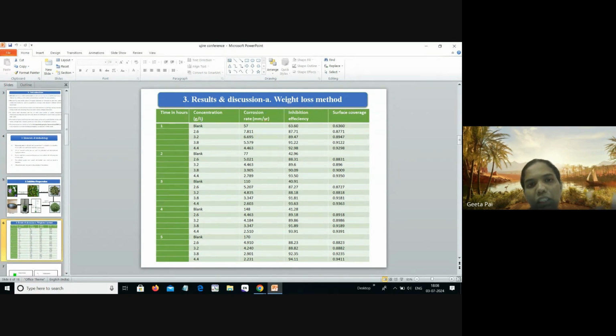From this result, it can be confirmed that from 1 hour to 5 hours in the absence of the inhibitor, that is, especially in the case of the blank solution from 1 to 5 hours, the corrosion rate value is very high. As the inhibitor concentration increases from 2.6 to 4.4, the corrosion rate decreases, but inhibition efficiency goes on increasing. So for 4.4 ml for 1 to 5 hours, we got a maximum inhibition efficiency of 94.11%.